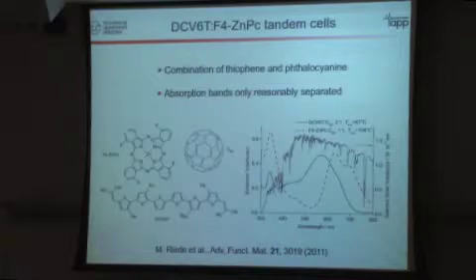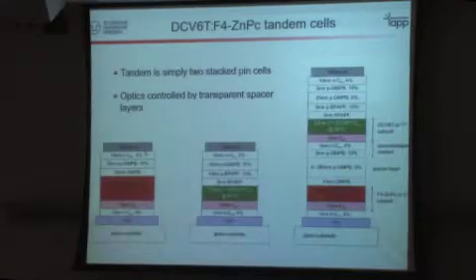and just show you some results which we published already some time ago, where we did such a tandem cell using a thiophene and again a phthalocyanine, in both cases with C60. As you can see in this case where we use organic materials, the overlap is significant. This is not ideal. We would actually need a larger gap between the two materials. But producing this cell is fairly simple. You have two individual cells and you simply stack them on top of each other.